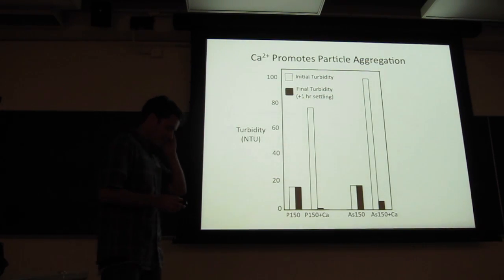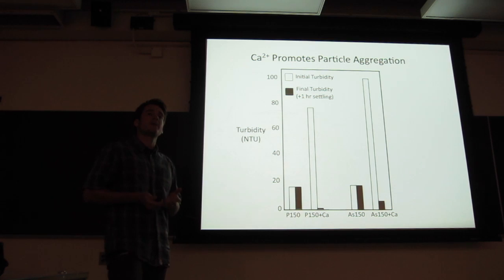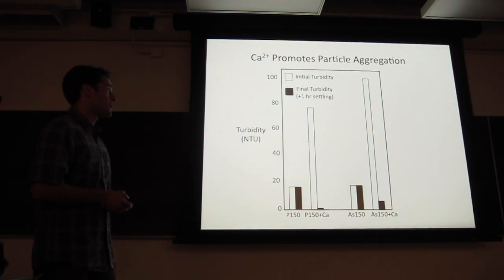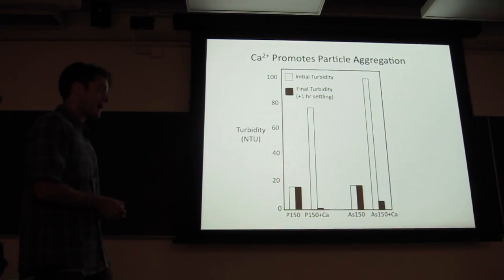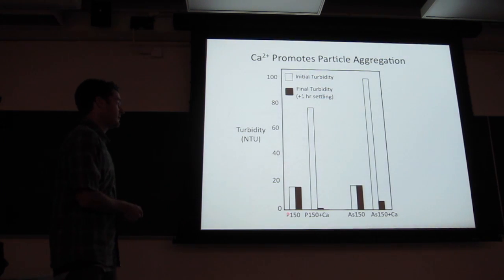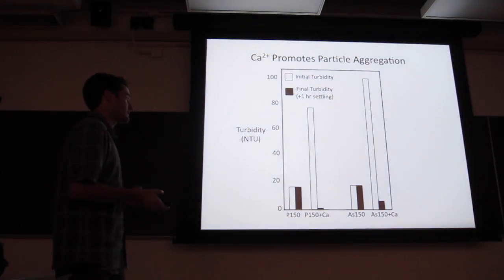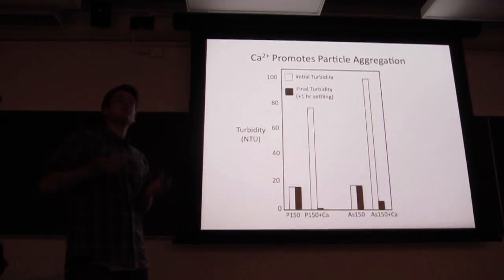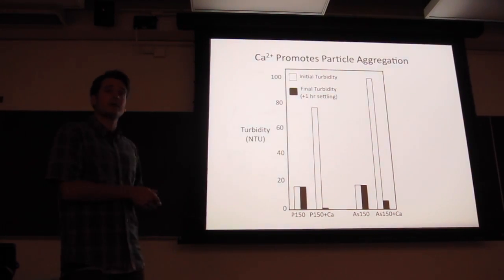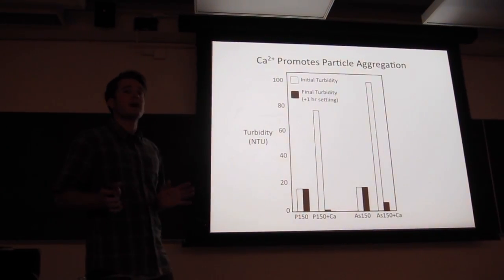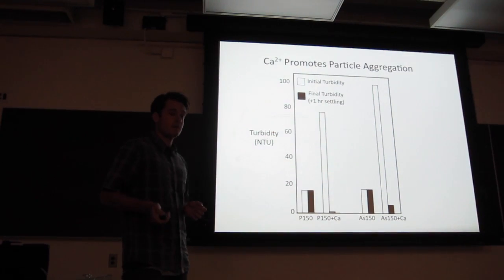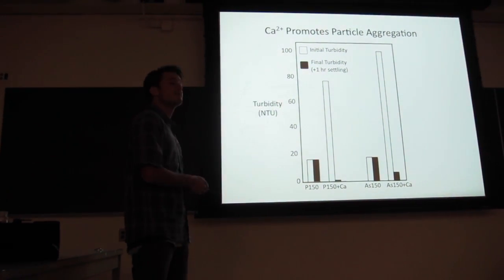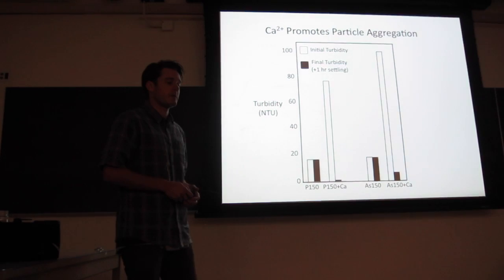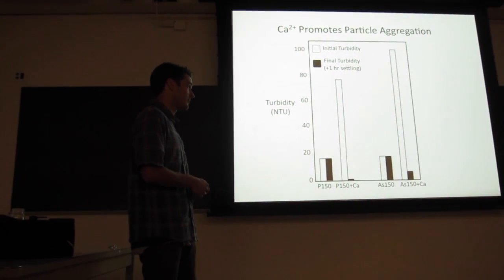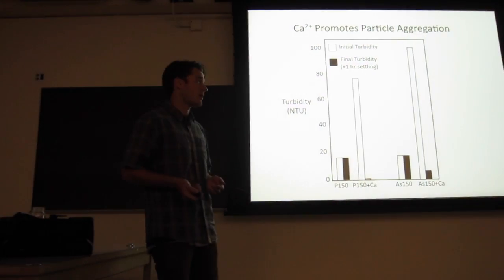Okay, so the first of the data, again, this is the most macroscopic measurement that we've made. It's these turbidity measurements. So in the absence of calcium, this P150 and AS150 samples, we see that there's a lower initial turbidity, and that's due to colloidal stability. So these suspensions look translucent, and they don't settle at nearly any kind of practical time scale. So these kinds of precipitates actually pose a problem in field treatment because it's very difficult to remove colloidally stable precipitates from treated water at low cost.